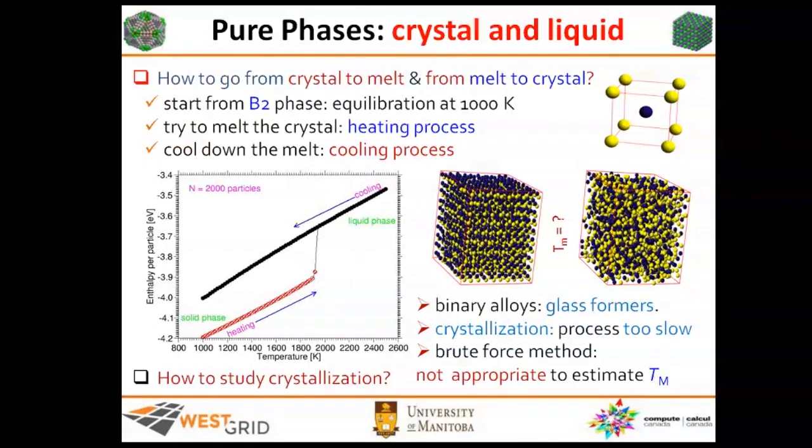So you have your system, which is a crystal in the middle, surrounded by the liquid. To obtain such a system, we start from a simulation box elongated in one direction. Using MD simulation, we freeze the atoms in the middle, then run the simulation at high temperature to melt the two parts.